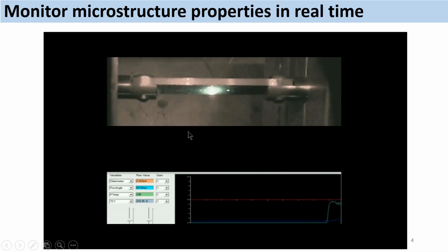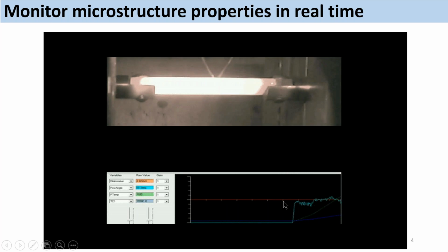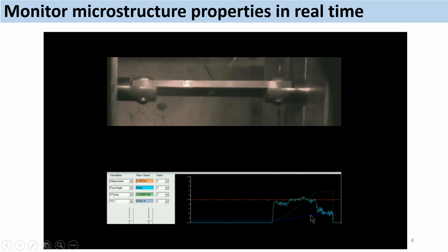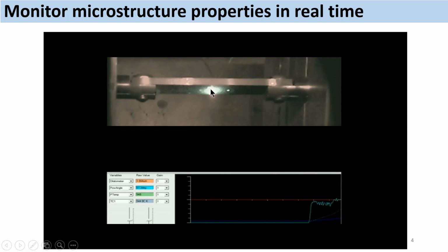So here is a little video in which I have recorded a heat treatment of a flat sample, which has been submitted to a welding cycle. So it's a very rapid heating and a very rapid cooling. What you could see here, a bright spot in the center of the specimen, is the laser firing periodically on the sample.